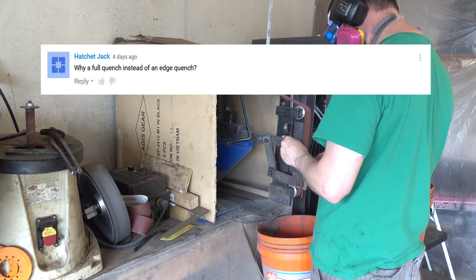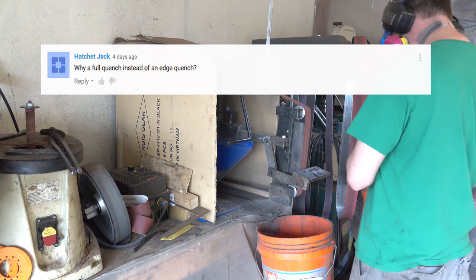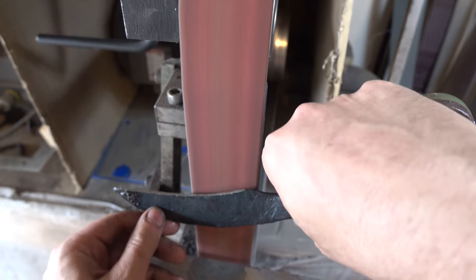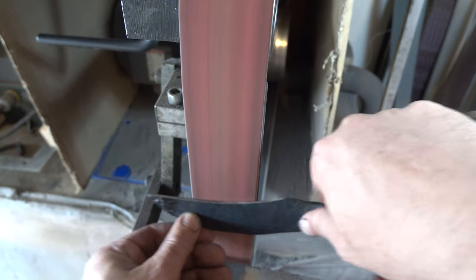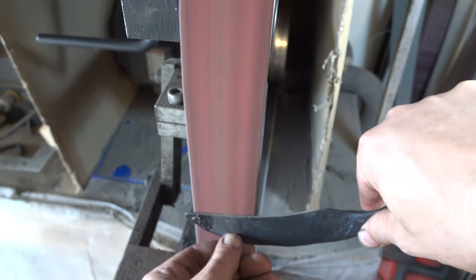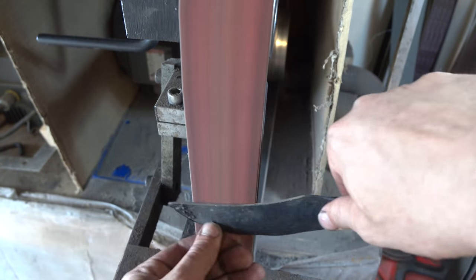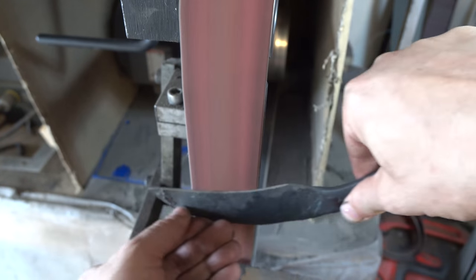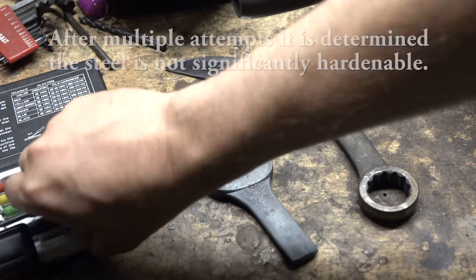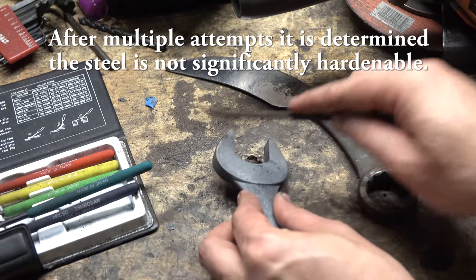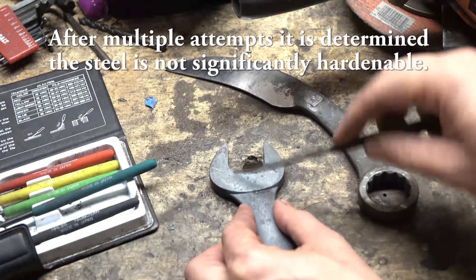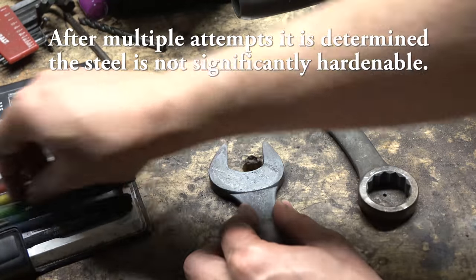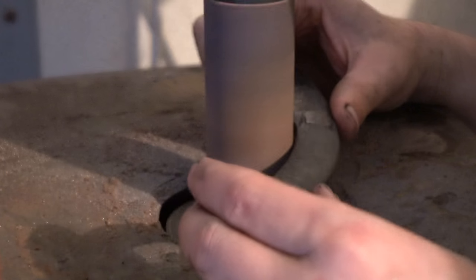Hatchet Jack asks, why a full quench instead of an edge quench? Edge quenching hardens the edge but not the spine or the handle of the knife which are left soft or springy which lessens the vibration transmitted to the user. And some steels edge quenching can leave a quench line similar to a hamon which may not be desired cosmetically. In shallow hardening steels edge quenching is probably not that much different than full quenching and some people feel like it even increases the chance of warping or micro fractures.